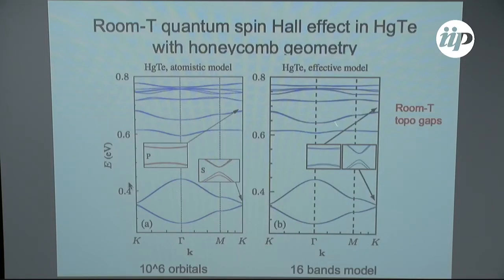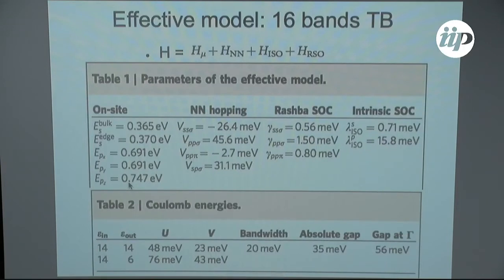And you can see that indeed, when you study both cases, you can show that this gap is topological. So simply by impinging holes in mercury telluride and patterning a honeycomb structure on the nanometer scale, you are able to get the quantum spin Hall effect at room temperatures. Now the experimentalists just have to realize it. It's not that easy.